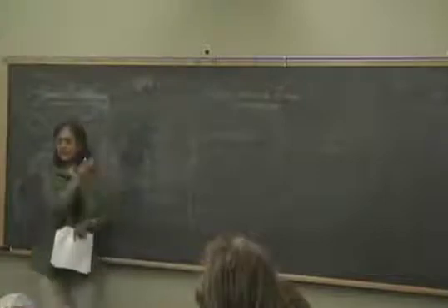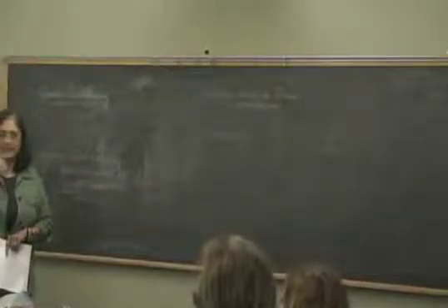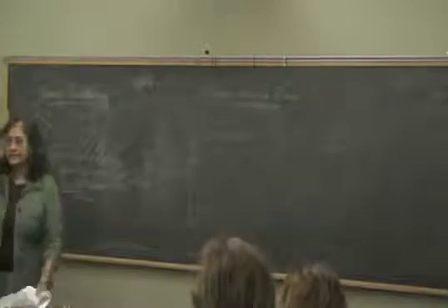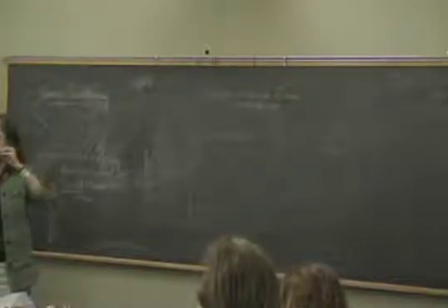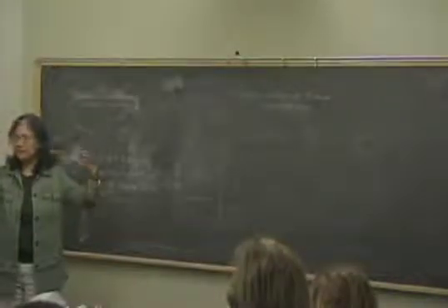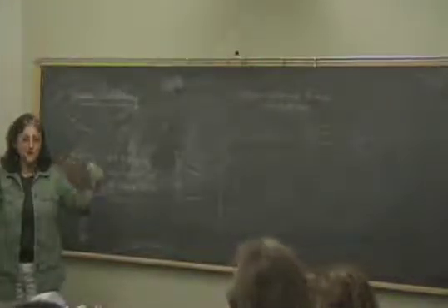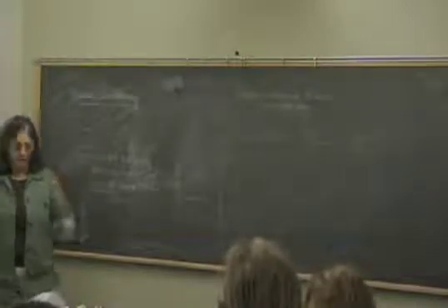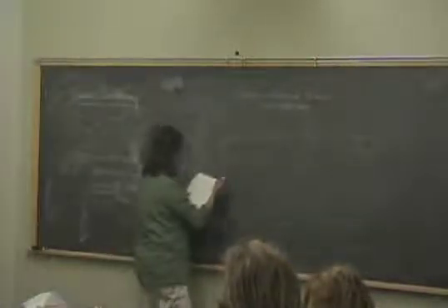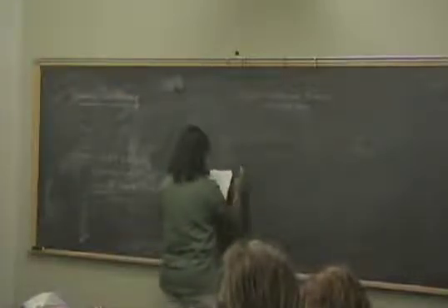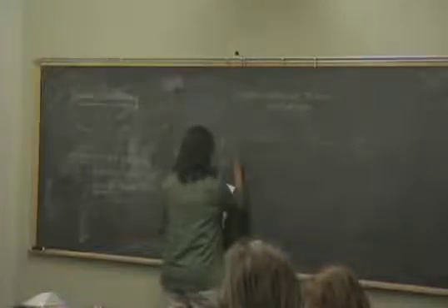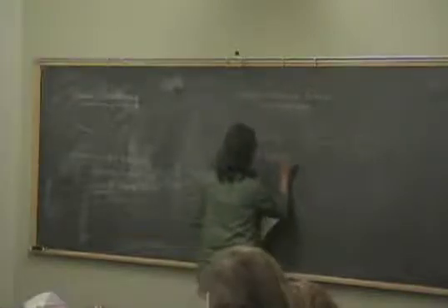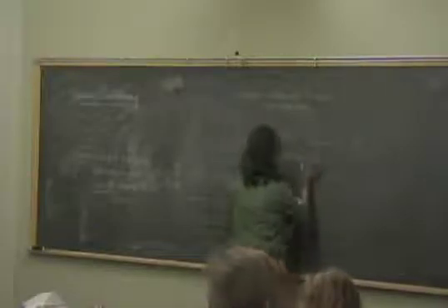And you can see that you all remember from your E&M class, when you have pointy objects, the electric fields are very concentrated at the tip, right? So we worked out the plasma oscillations of the sphere. But if you make it more and more elongated, then the surface plasmons are going to be modified depending on the shape of your metal object. So again, I don't want to get into detail, but let me just write down: electric field is enhanced.